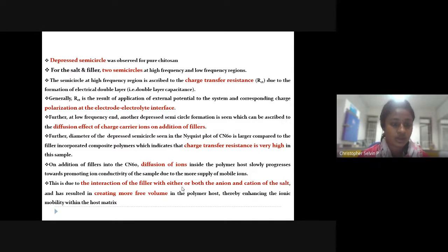To explain, the semicircle seen in the Nyquist plot of CN60, that is for the salt, is larger compared to the filler incorporated composite polymers, which indicates that charge transfer resistance is high in this sample. On addition of fillers to CN60, the diffusion of ions inside the polymer host slowly progresses towards promoting ion conductivity of the sample due to more supply of mobile ions. The interaction of the filler with either or both the anion and cation of the salt has resulted in more free volume, thereby enhancing the ionic mobility within the polymer host.